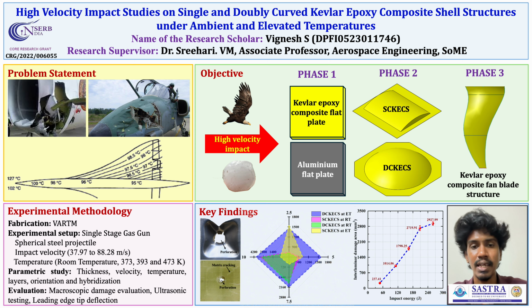The key findings of the research were: the Kevlar-Epoxy composite flat plate dissipates the energy in the localized contact zone, whereas the aluminum flat plate dissipates the energy globally in a deformed mode. In the curved shell structure impact study, a higher central curvature height, from 2.5 mm to 10 mm, resulted in reduced localized permanent deformation and increased interlaminar damage area in both single curved and doubly curved Kevlar-Epoxy composite shell structures at room temperature impact.